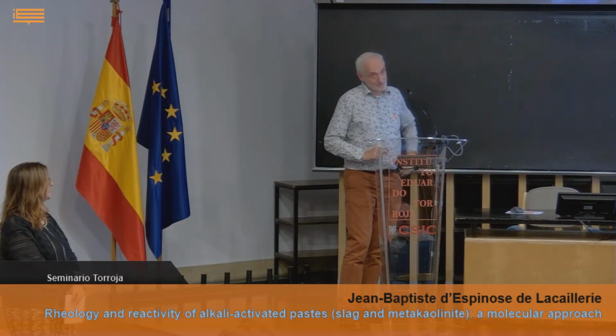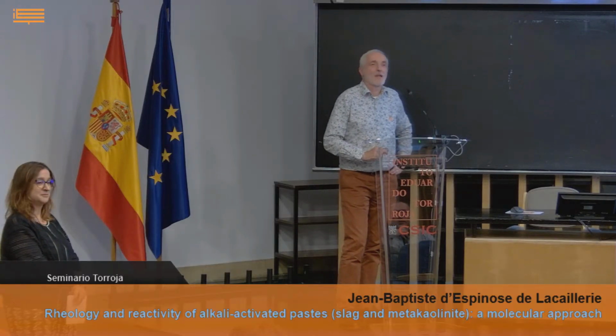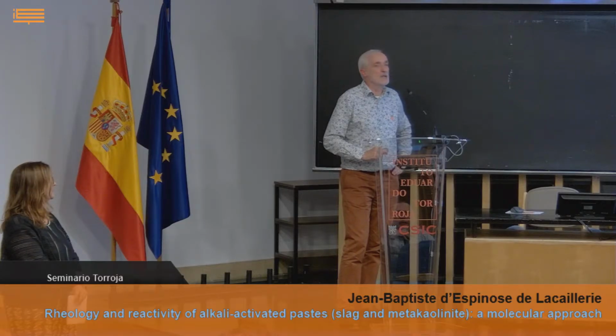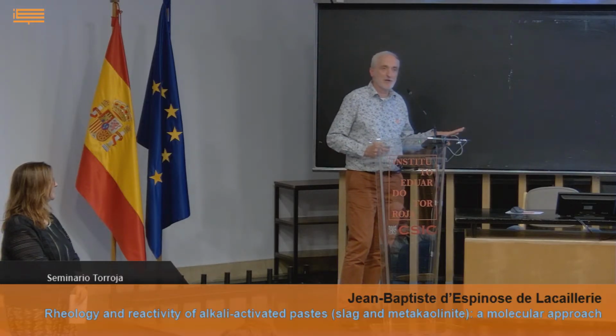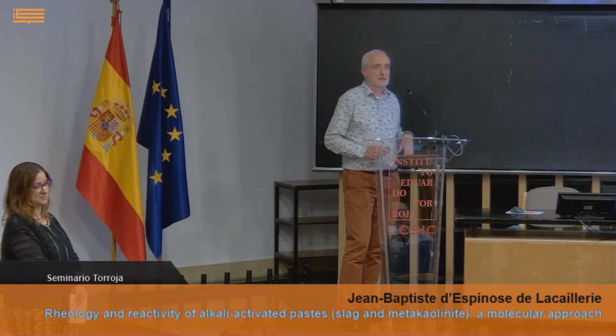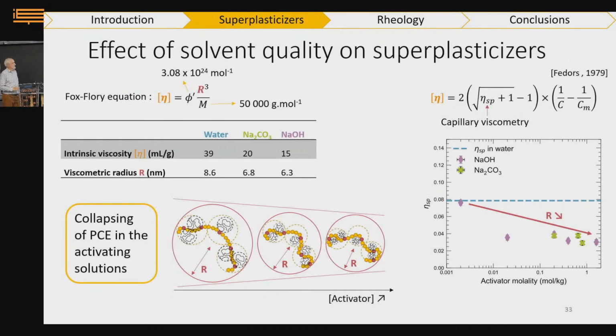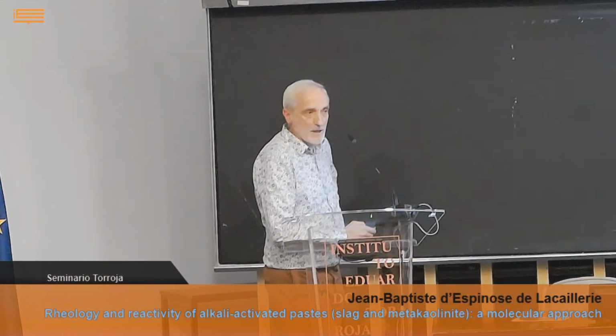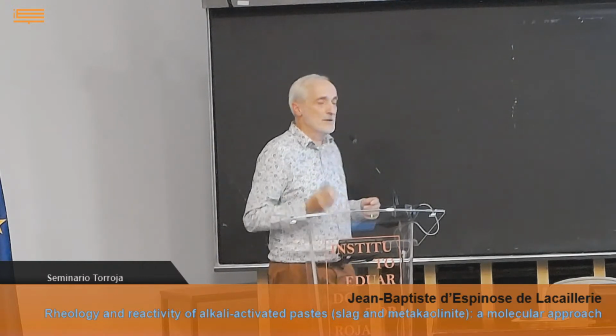No. I was a member of the jury some years ago when you had alkalis in distilled water. With respect to the rheological behavior, or with respect to the polymer conformation? The capillary viscosity of the solutions. On 33, not 24. Yes, this one. Because the intrinsic viscosity here is computed from the viscosity that you measure, and then you have to relate it to the viscosity of the solvent. Yes, this is by comparison with the pure solvent. So it is accounted for, right? The pure solvent viscosity changing because of the ions. Yes, yes. Okay, that was your question. I thought it was in terms of the conformation of the polymer.